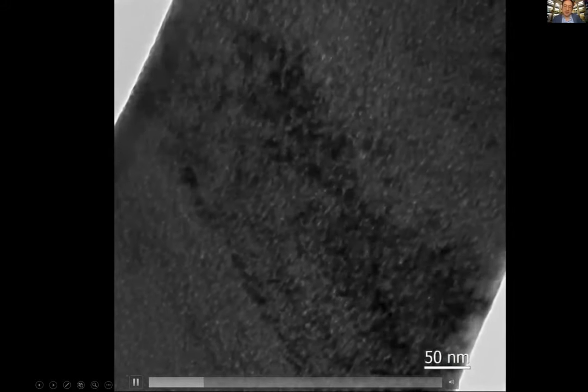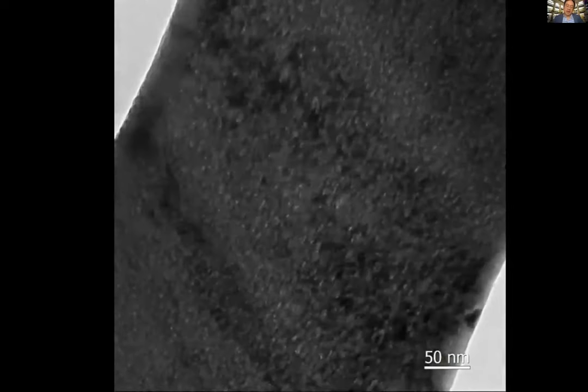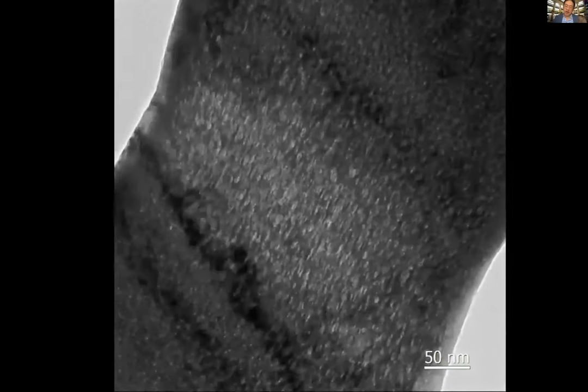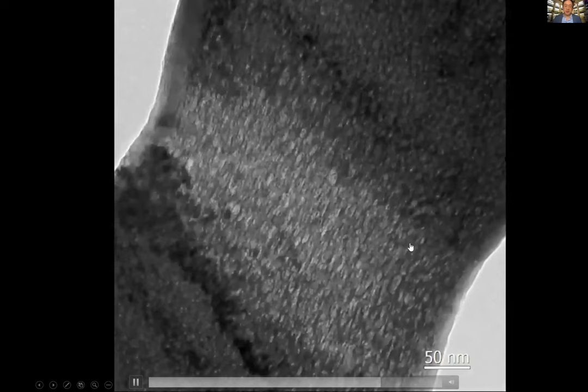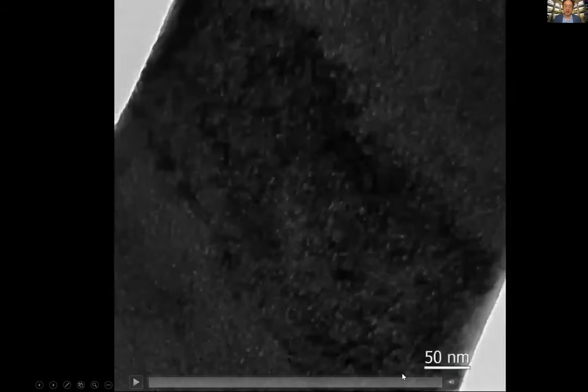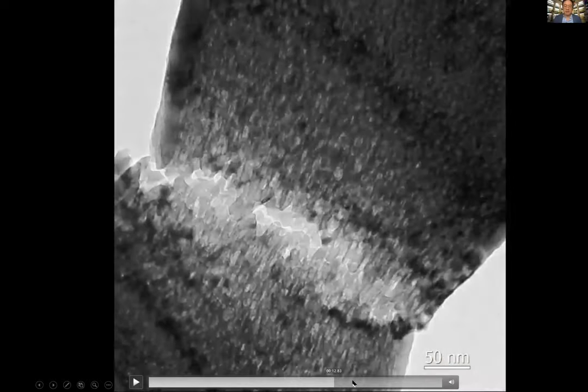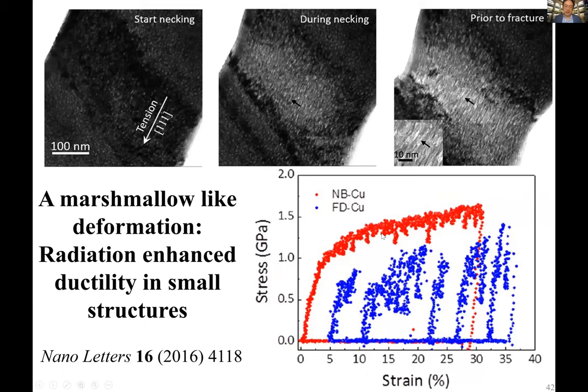What is surprising is when we deform this single crystal, it appears very ductile. Generally, helium embrittles the macroscopic material. What is surprising is that when we inject helium, it actually makes the system appear more ductile, even more so than without the helium bubbles.